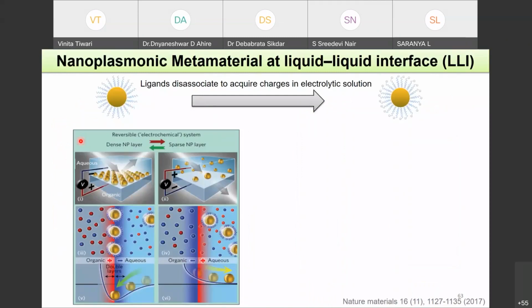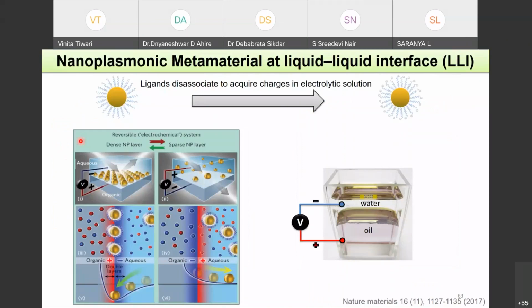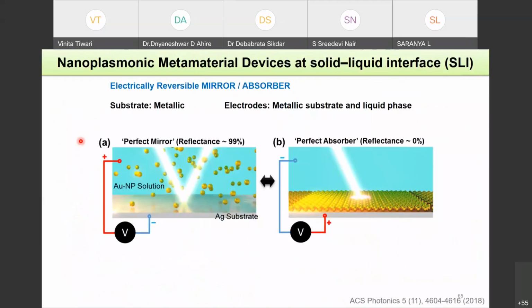So going back to the application, we have already seen that this allows you to make a reversible window mirror system at liquid-liquid interface, right? Now, when you go and make the system on a solid-liquid interface, it means you have a silver substrate which you are now using as a negative electrode, and then you have a gold nanoparticle solution, and you keep an electrode which is a positive electrode. And these nanoparticles, like before, they are negatively charged. So when water is positively charged and the nanoparticles are negatively charged, they are all swimming or floating in the water layer. So what will happen?